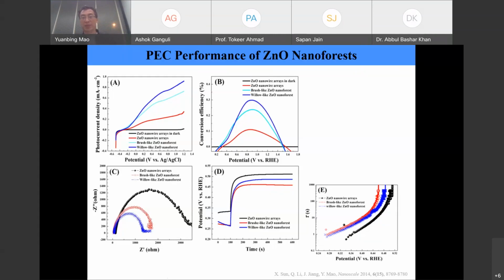It helps us to understand why the willow-like nanoforest would have the best electrochemical performance, right? But there are other factors as well. One thing is we look at the resistance, the charge transfer resistance, and we can see that the willow-like zinc oxide nanoforest actually has a very nice half curve. And this resistance is actually the lowest compared with the other two samples, right?